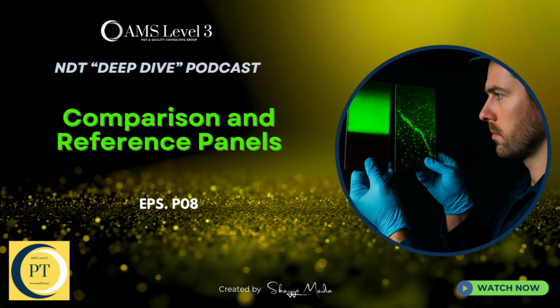Okay, so if the high-tech LCS are tricky to reuse, what came before? Let's talk about the older ones, the quench-cracked aluminum comparator blocks. Ah, the historical standard. You'll still see them mentioned in codes like ASME, AMS 2644, but mostly as a reference point. The general feeling now, though, is they just don't offer the discrimination needed for modern, high-sensitivity penetrants.